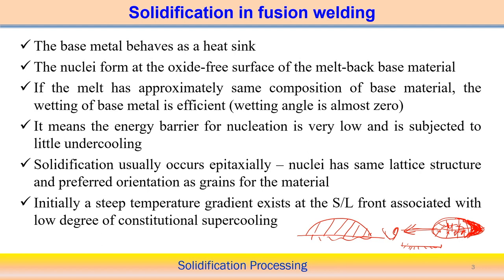Now with this, epitaxial growth of the metal occurs in one particular direction during the welding process, and of course we can observe that initially a very steep temperature gradient exists at the solid liquid interface, associated with the low degree of constitutional supercooling that we have already seen. A steep temperature gradient exists at the solid liquid interface. So this is the typical characteristic of a fusion welding process when you try to understand the solidification associated with it.